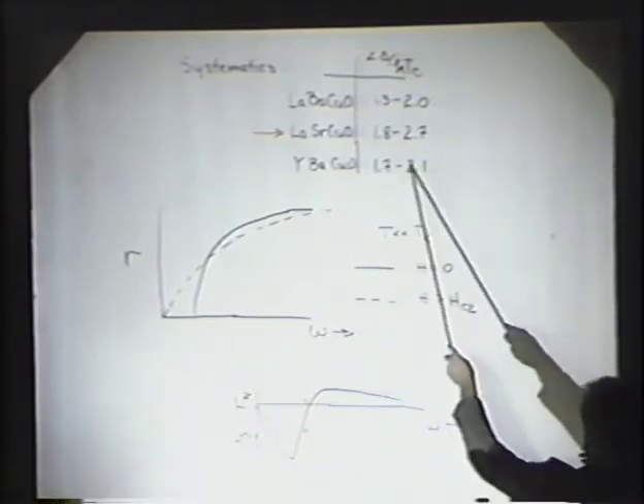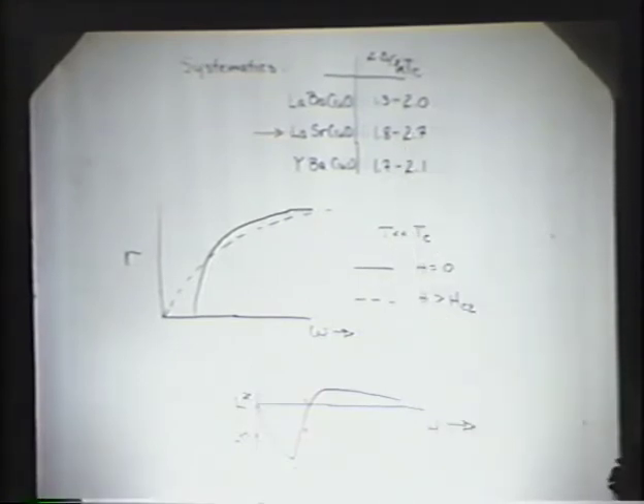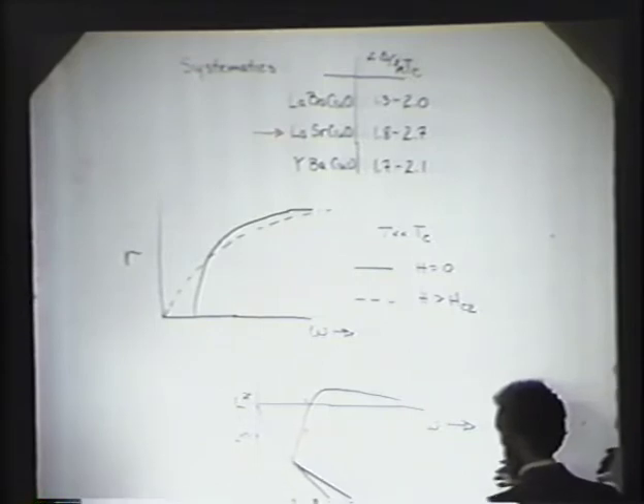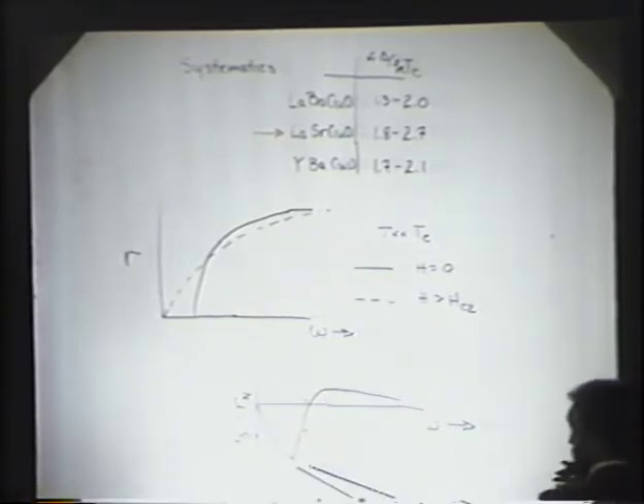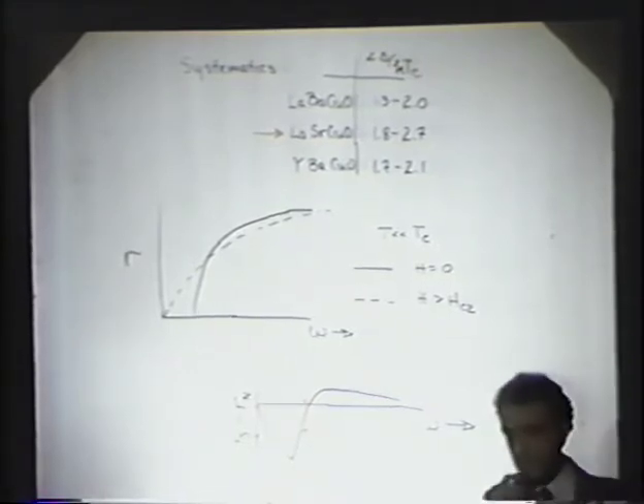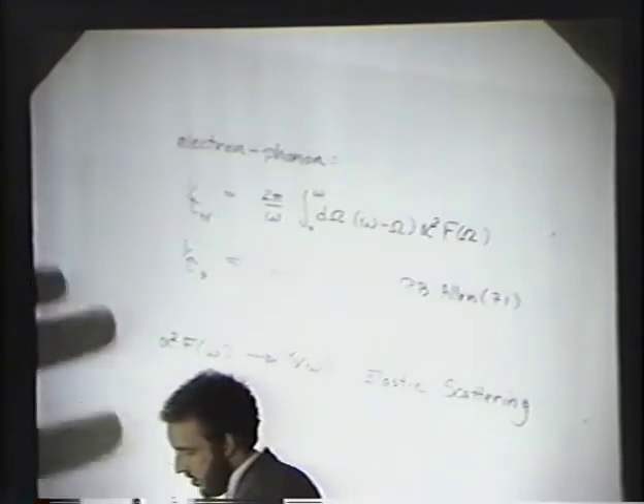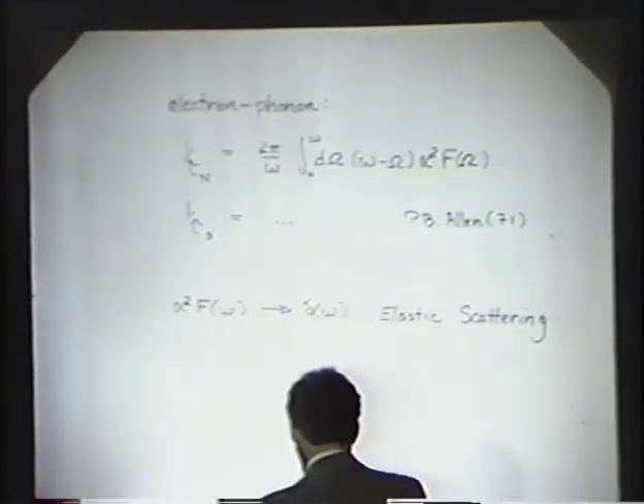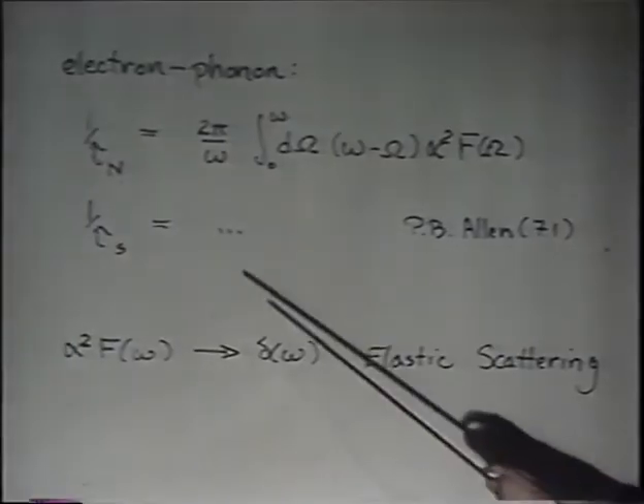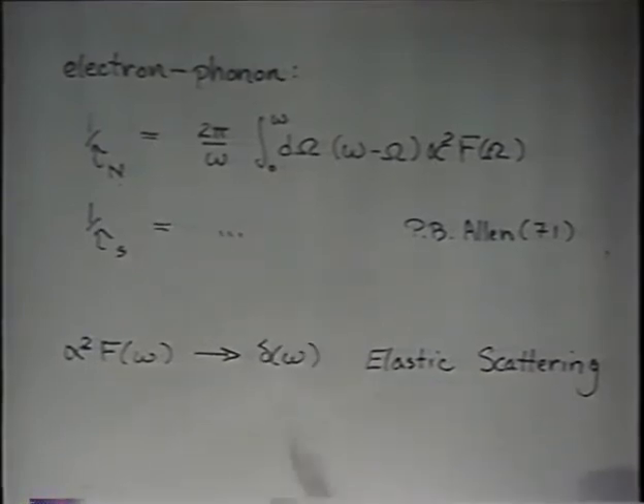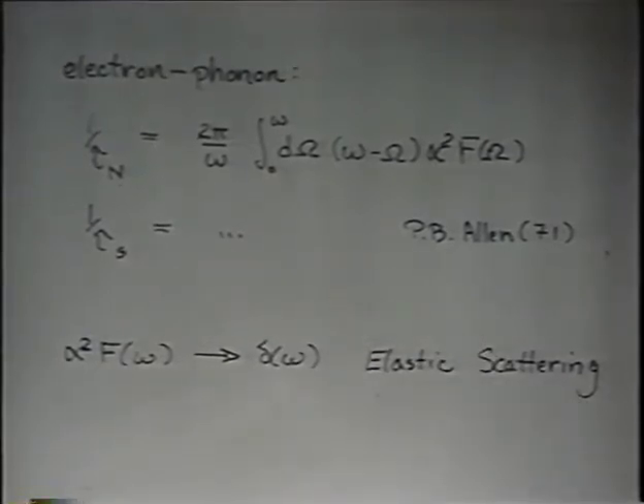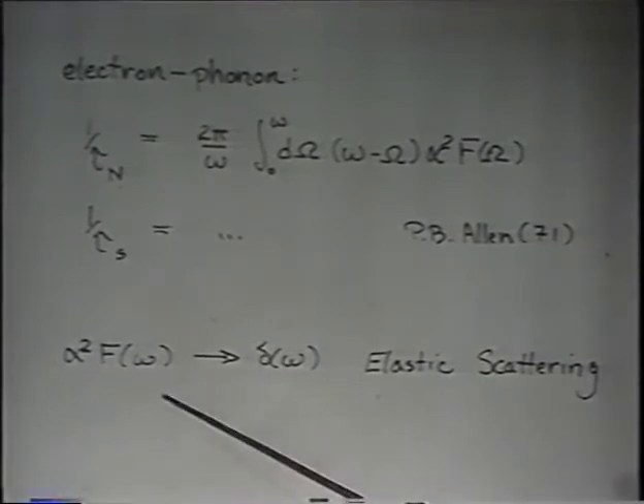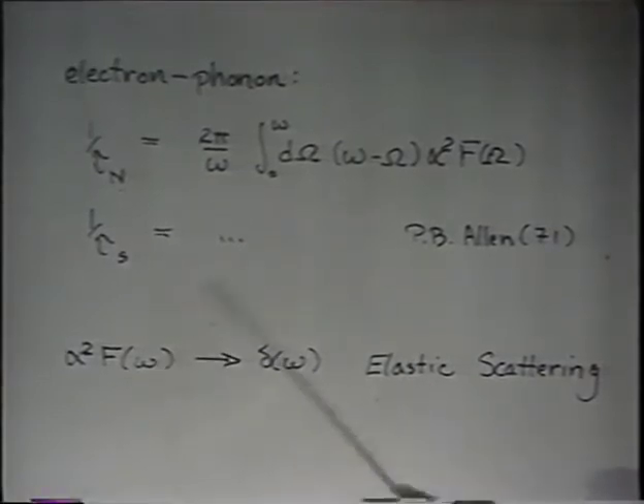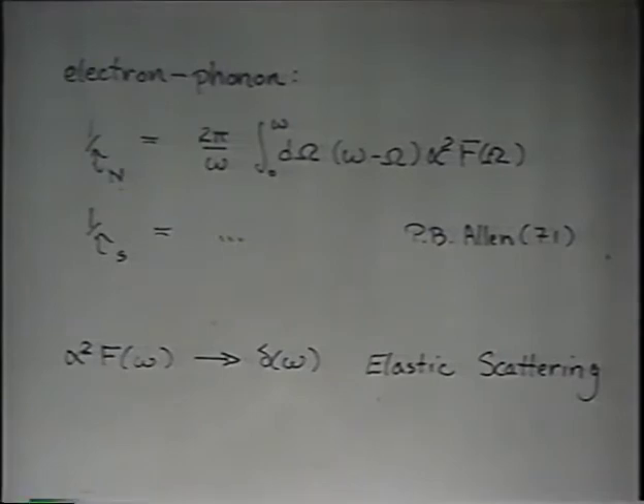Now, the variation in numbers here isn't a sample-dependent thing. It's just that it depends where we choose to define 2 delta. Is it the peak, or is it the inflection point, or is it the crossing? And you'll see that data. So just before we go to the data, if we think about the Holstein process or an electron-phonon interaction, we can write down an expression following Allen for the scattering rate of the normal state and a similar expression for the superconducting state. And just to mention, if you have elastic scattering, you can use the same formalism and replace the alpha squared F, which is the electron-phonon coupling constant times the density of states, by a delta function expressing elastic scattering.